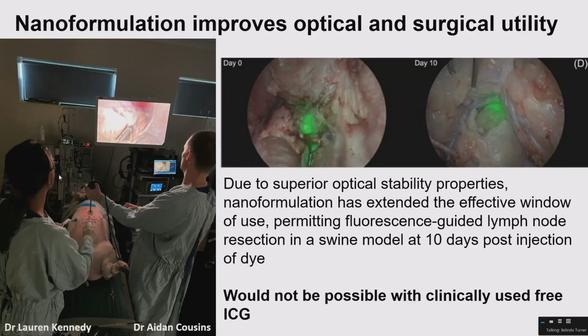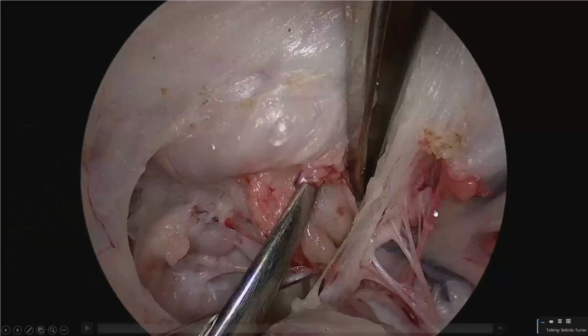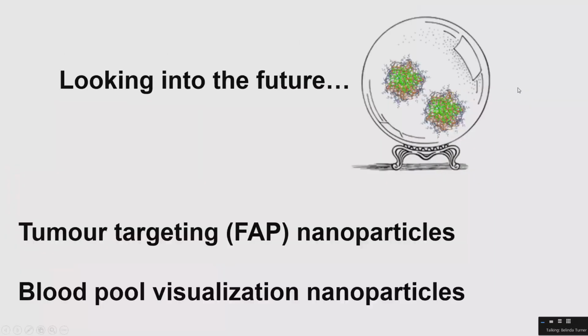So this is sort of one of our setups for our endoscopic surgeries. So we've got Dr. Lauren Kennedy and Dr. Aidan Cousins. And here we've got a lymph node on day 0 that's been injected with our ICG nanoparticles, and then there's also signal still appearing in day 10. So due to the superior optical stability properties, we're able to extend the effective window of use, permitting surgery for much longer time, which would not be possible with clinically used free ICG. So looking into the future for these particles, we're looking into targeting FAP as well for tumour delineation, but also using it as a blood pool visualisation.